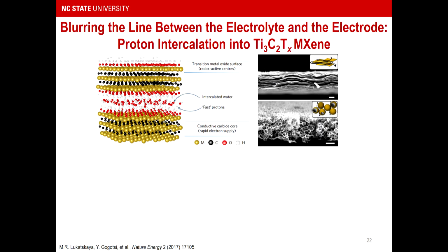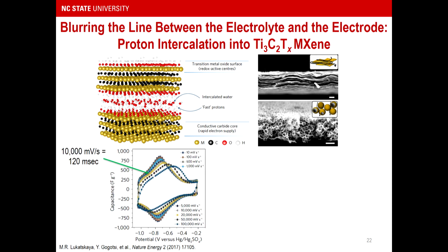And from the Faradaic side, you have materials such as MXenes, which are derived from selective etching of transition metal carbides that contain layers of what could be called an electrolyte that potentially could be enabling very fast proton transport and access to surfaces throughout their entire volume, giving rise to cyclic voltammograms that look like this with very reversible Faradaic peaks, but now we're talking about cyclic voltammograms being run at 10,000 millivolts per second, something that before, I think, the past few years, nobody would have thought would be possible with any type of Faradaic mechanism.